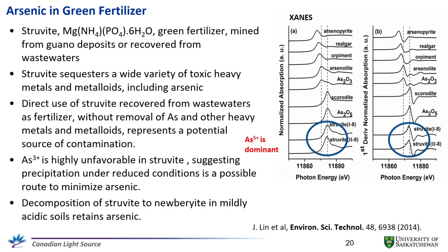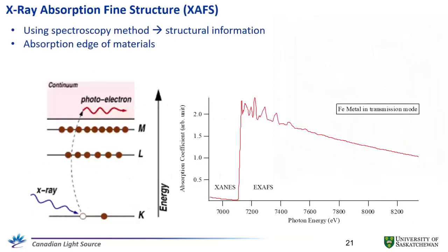This will reflect in the X-ray absorption. So by comparing the measurement from your sample to some reference materials, you can easily identify the element, what the element is and what the valence is. And sometimes if you really do very careful work, you can even detect the local environment of this element, which is the next thing I'm talking about.